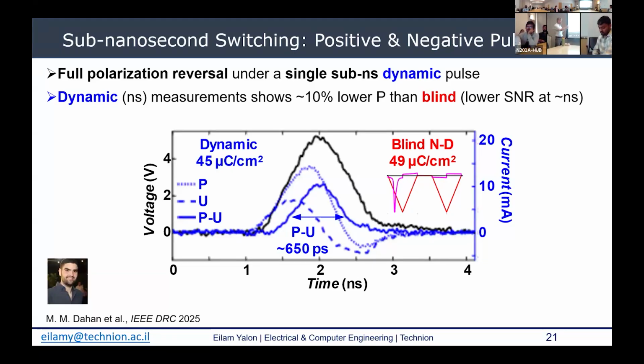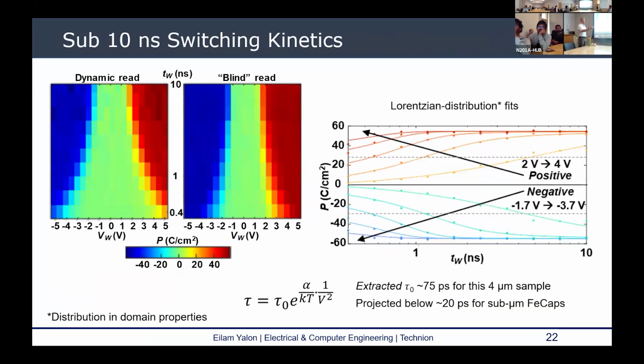With the same technique, if we go to 10 nanoseconds and longer, they match. So we know that at the short time scale, we lose some of the signal because of lower signal to noise. But overall, we get a pretty good picture of the dynamics of the switching, and we get the net polarization charge from the blind readout. So with that, we can now vary the voltage amplitude and pulse width down to short time scales.